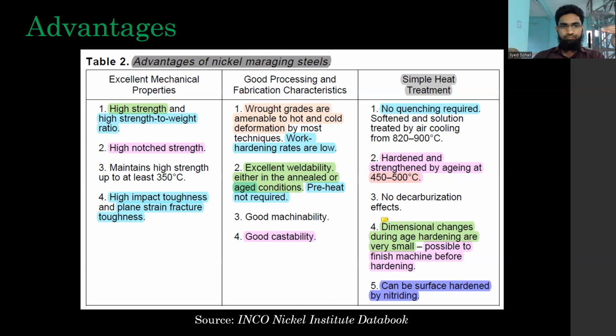Another advantage, in comparison with similar strength materials, is that preheat is not required. In welding, generally preheat is done to avoid cracking issues, etc. Preheat is not required. Another distinguishing feature is that pre-weld and post-weld treatments are also not required when it comes to welding.